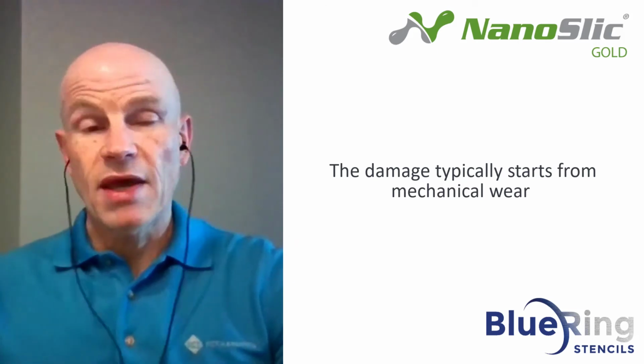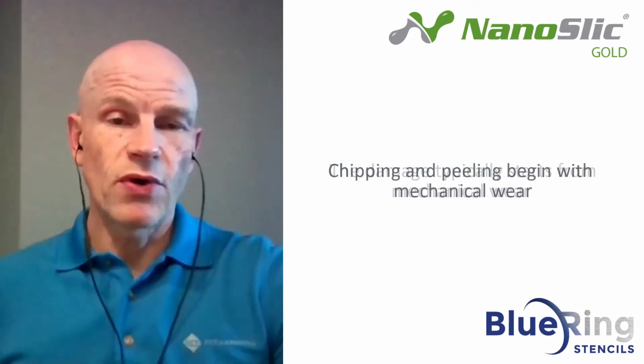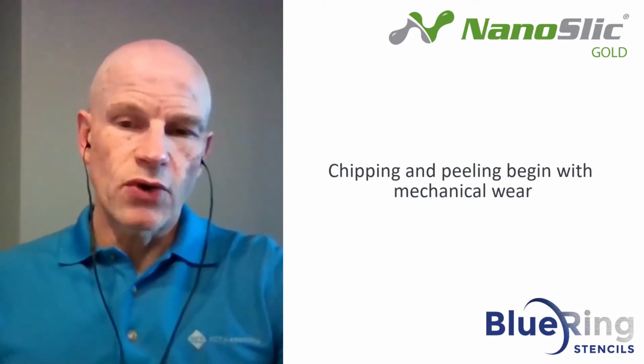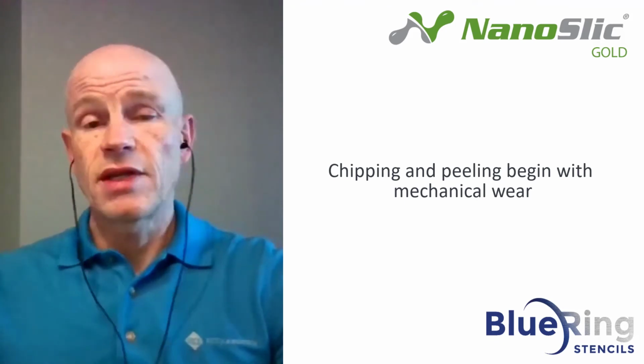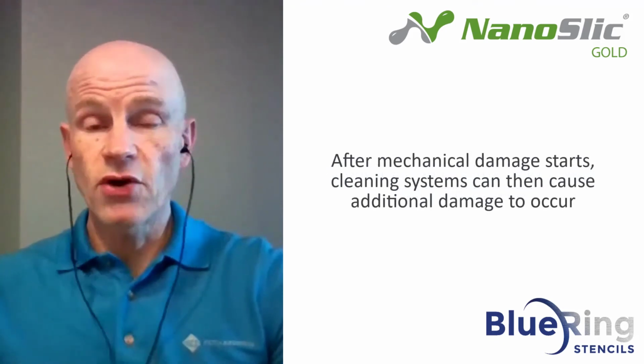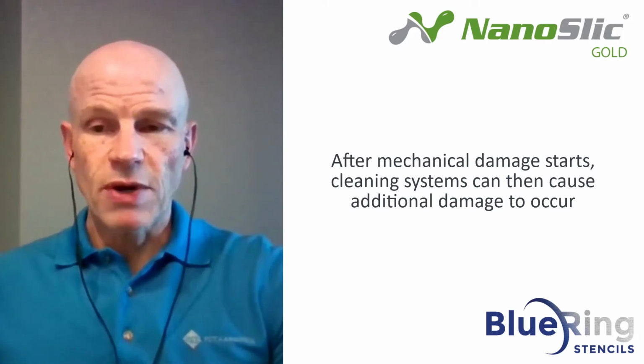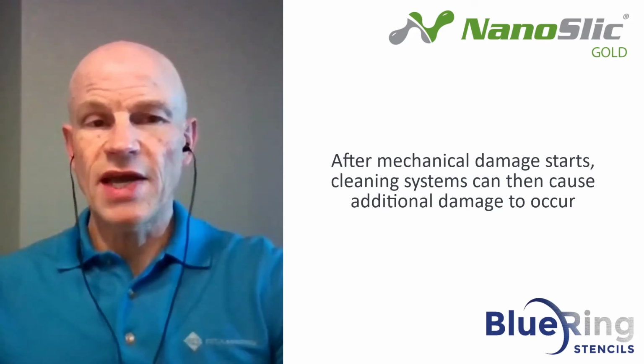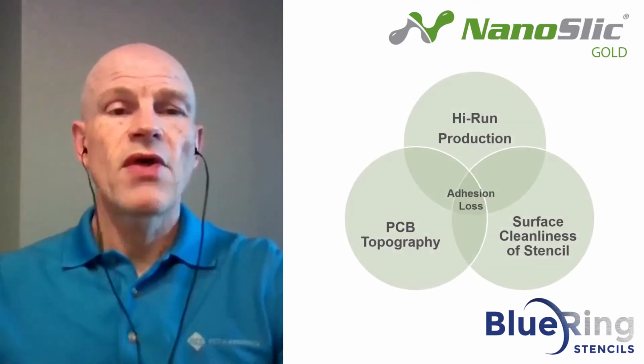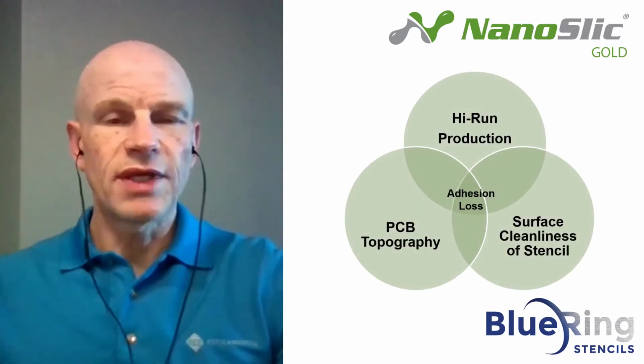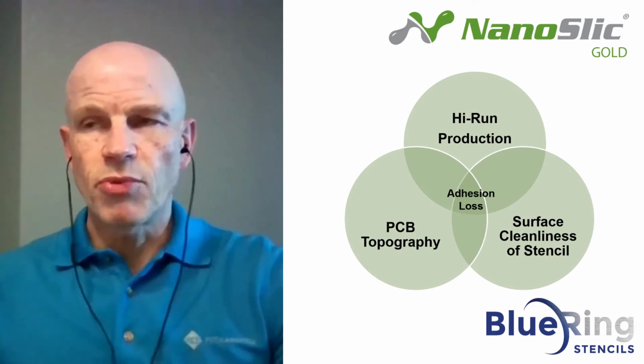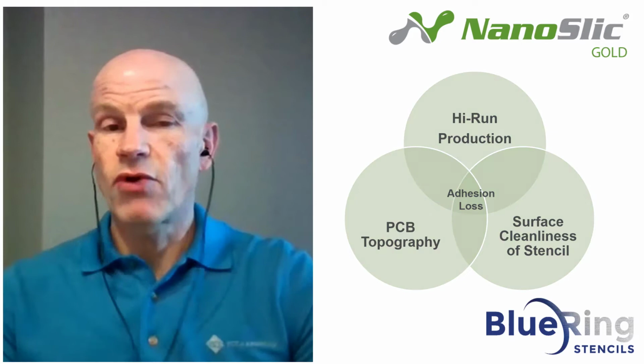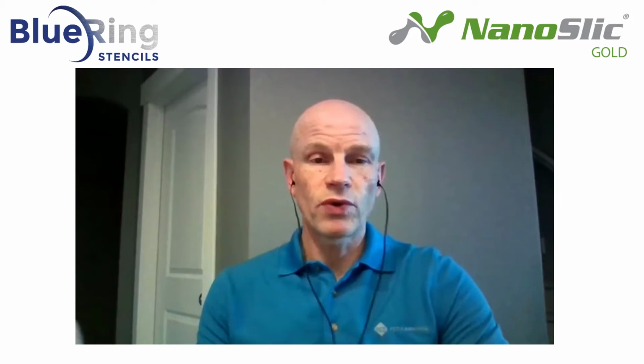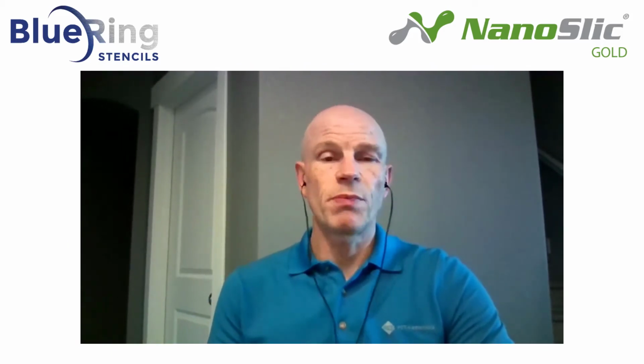Now, there are cases where that mechanical damage can start, where there's some chipping going on in the coating, and then you put a coated stencil into a cleaning system, especially a high pressure spray and air type system. The spray pressure itself will impinge on the edges of wherever the coating has begun to crack, and it'll continue to break it away slowly over time, chip it away. So you can pull a stencil out of the cleaning system, especially a high pressure spray and air system, and it may look like the cleaner stripped the coating off, but really the coating started chipping due to some mechanical damage that occurred previously.